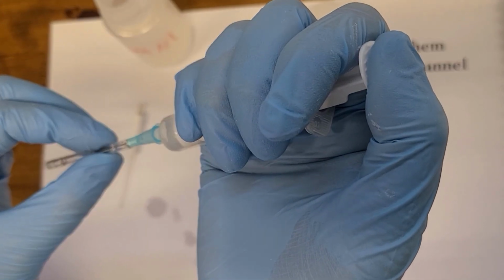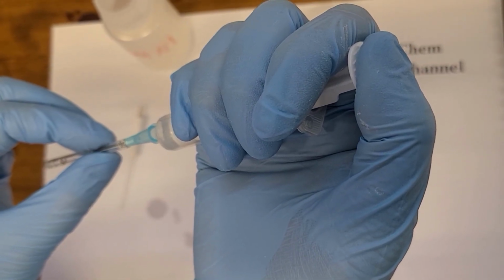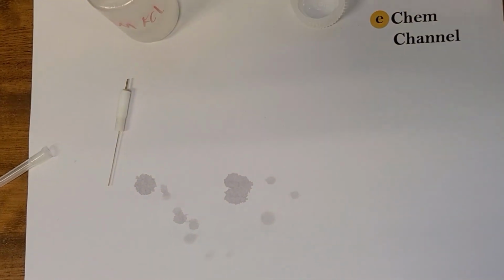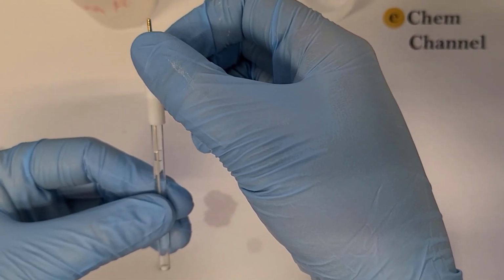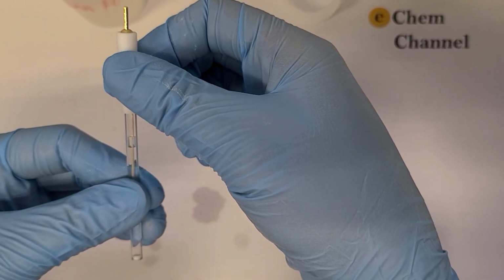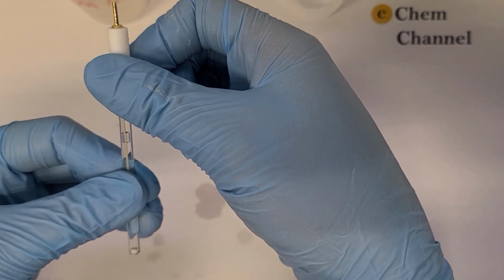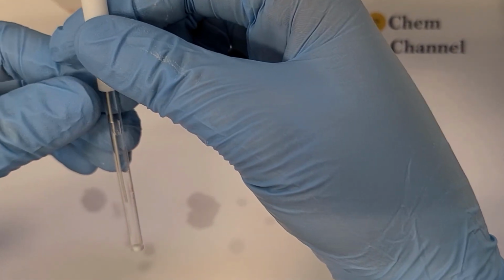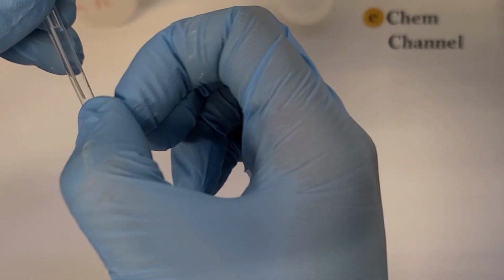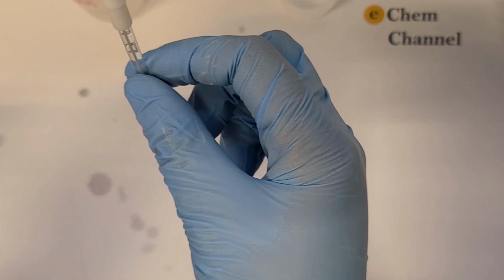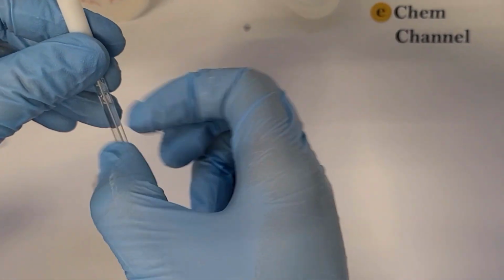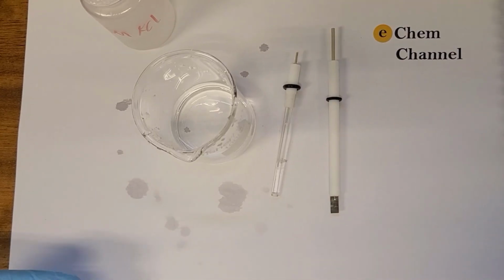We then refill the tube with potassium chloride and put the freshly polished silver wire back into the tube. Again, we get rid of the bubble. And then we need to recoat the silver wire with the silver chloride.